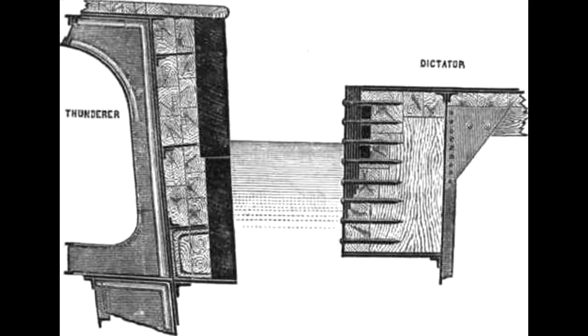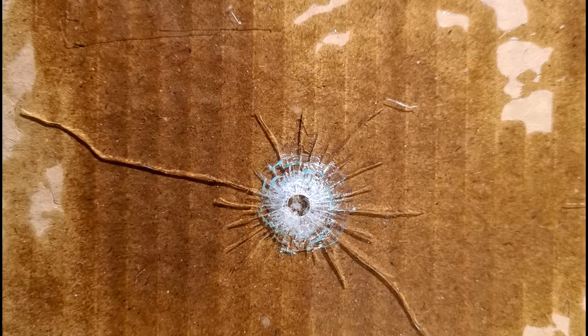But the general point of one material supporting the other is borne through. Let's see what happens now. So here's our cardboard and glass analog to, say, HMS Warrior's teak and iron. There goes the steel pellet, and, well, it's punched a hole through, but if we take a somewhat closer look at the damage, you'll see that not only is the resulting hole in the glass considerably smaller, but also the crack propagation is considerably less, and the glass plate is still there, it hasn't fallen down.